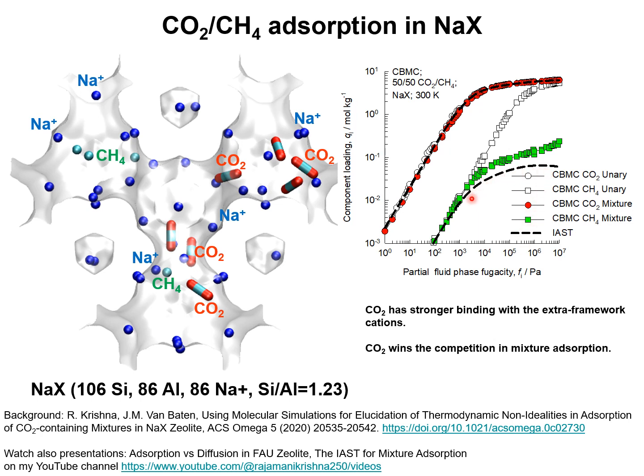The dashed lines are the calculations of the mixture adsorption loadings using the ideal adsorbed solution theory. The IAST also anticipates that methane will lose the battle for mixture adsorption. There are quantitative differences, albeit slight, between the IAST predictions and the values determined from configurational bias Monte Carlo simulations, and this is due to the inhomogeneous distribution of the guest molecules within the pore space.